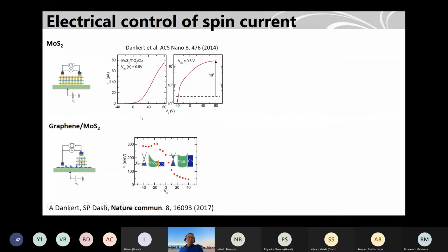There may be two things happening together. First, when you put MoS2 on top of graphene, you induce a spin orbit coupling, so that reduces the overall spin signal. Then on top of that, when you apply a gate voltage, because MoS2 is a semiconductor, it is turned on when you apply a positive gate voltage, since it's an N-type semiconductor. This is the log scale plot of the same.